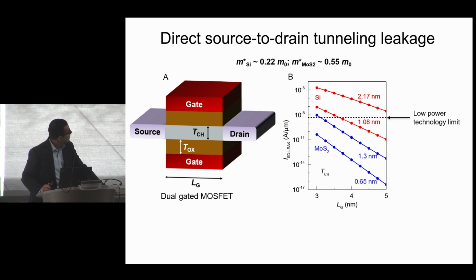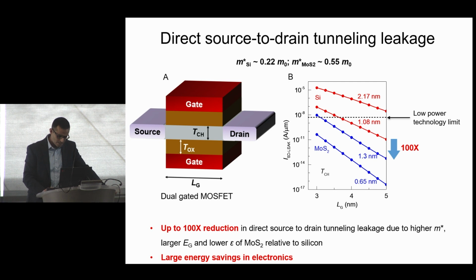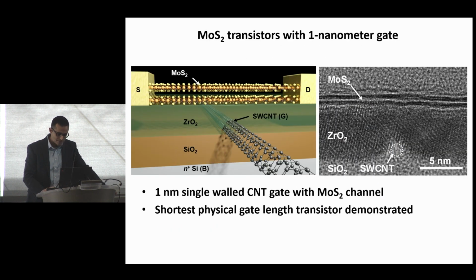Now, if you move to MoS2, in this case 1.3 nanometer, which would be bilayer, you can see that for a material that is a little bit thicker than silicon, you already get about 100x improvement in leakage current. And that's not because of thickness, that's purely because of effective mass and the in-plane dielectric constant. And of course, if you move to a monolayer, then there is a couple of orders of magnitude more reduction in the leakage current. So that's where the motivation for using some of these 2D materials comes about. Now, around that time, we wanted to validate these models. We were just doing simple simulations, and the question was, how accurate are these simulations?